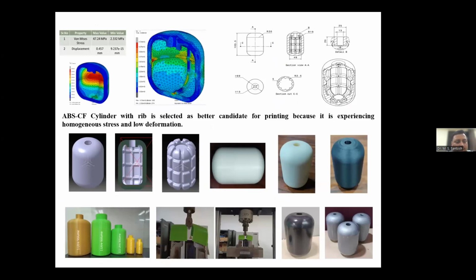The initial images show that the internal rib structures are being provided within the cylindrical models. Although the ribs are evident in the simulated model, when the cylinders are actually printed using a 3D printing system or an FDM process, you don't get to see the ribs on the external surface of the cylinder. But obviously, the ribs are present within the cylinder. We have not cut open the cylinder to show that, but those ribs are definitely present.